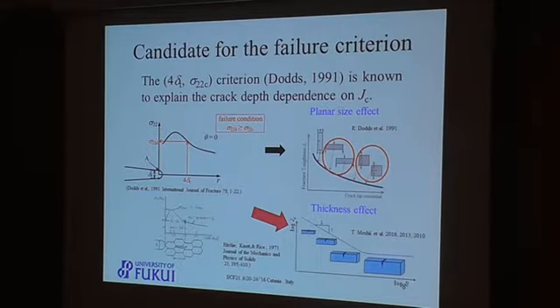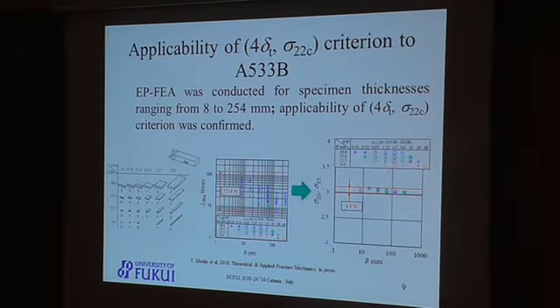For the failure criterion, we considered one of the modified Ritchie-Rice failure criteria, that is the 4 times CTOD sigma 22C criterion, which predicts the onset of cleavage fracture when the crack opening stress sigma 22, measured at a distance from the crack tip equal to 4 times CTOD, the crack tip opening displacement delta T, hereafter denoted as sigma 22D, exceeds a critical value sigma 22C. This criterion was validated as explaining the crack tip constraint dependence of JC and the test specimen thickness dependence of JC.